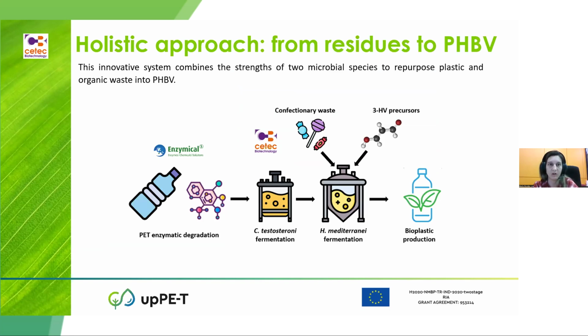So in the upPE-T project, we have developed a holistic approach to produce PHBV from this kind of residues. We have developed an innovative system that combines two microbial species to repurpose plastic and organic waste into PHBV. As my colleague Friedman from Enzymical has explained before, they are degrading the PET bottles through enzymatic hydrolysis. So what we are doing is using the mix of the PET degradation byproducts to feed Comamonas testosteroni, which is a strain able to metabolize the TPA and to produce biomass that can be further used in Haloferax mediterranei fermentation for the production of the PHBV, which is later transformed into bioplastic for different packaging applications.